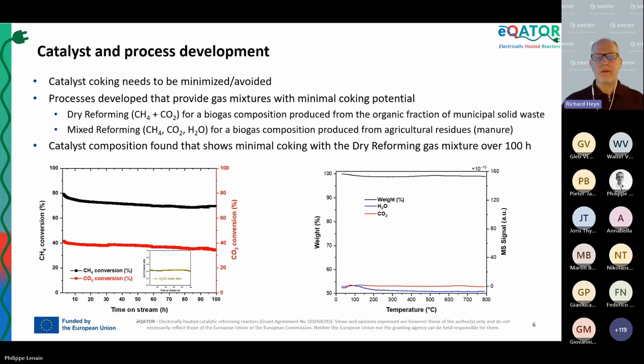And what we've been able to do is we have a catalyst composition that shows the minimal coking with the dry reforming gas mixture over 100 hours. So on the left-hand side, you see the stable methane and CO2 conversions, and we have a syngas ratio of about 0.4. And on the right-hand side, you see the coking profile of the catalyst after the reaction, and essentially there is no coking that is observed. So we have a very good starting point in order to have a catalyst system that we can integrate into our electrically heated reactors. So how do we do that? And I'll just show the examples for the resistive heating on the next slide.